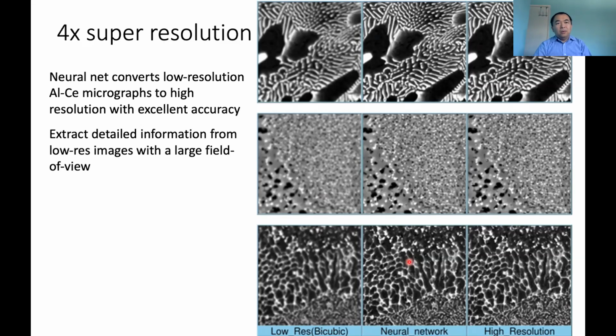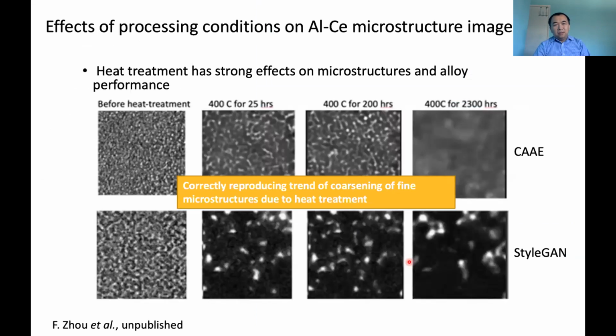As a second example, we are looking at the effects of processing conditions on the aluminum cerium microstructure images. If we perform heat treatment on the alloys, the fine microstructures of aluminum cerium tend to become coarser due to heat treatment. We trained a neural network model on this data set from Orlando's group. And indeed, we were able to correctly reproduce the trends of coarsening of the fine microstructures due to heat treatment.